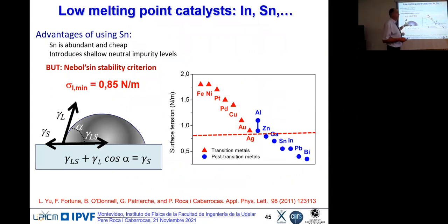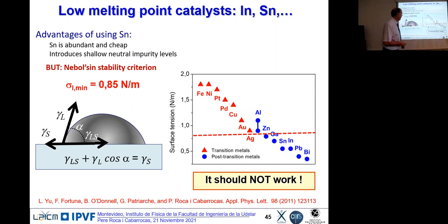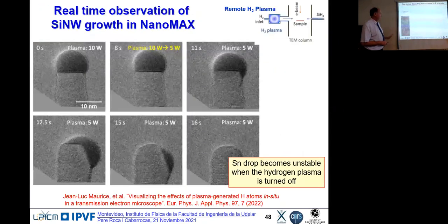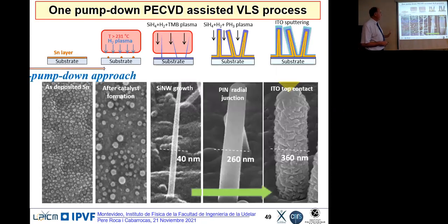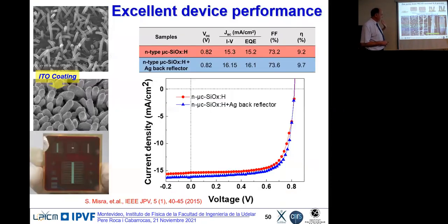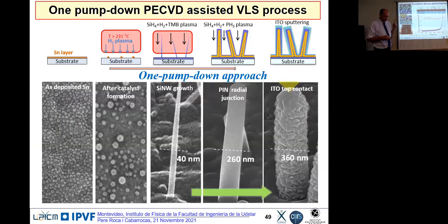In fact, what we discovered, and we can spend more time on it, is that we combine copper and tin, because if you have a bimetallic catalyst, you can have something which is solid, and then it will prevent the tin from spreading away. So we have the nanowire solar cells, a simple process.